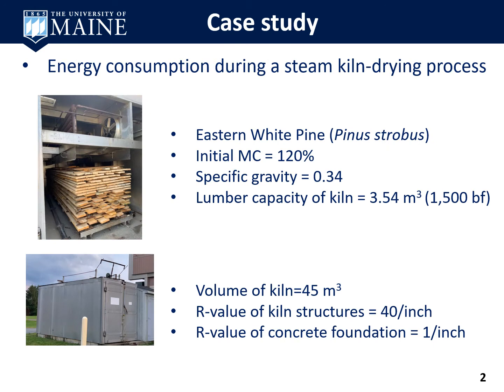Conventional wood drying process, also known as heat and vent drying, is regarded as an energy-intensive process. We did a case study to analyze how much thermal energy is used to heat the cold fresh air brought in the kiln. The wood species was eastern white pine with an initial moisture content of 120% and a specific gravity of 0.34. 1,500 board feet of lumber was loaded into a small steam kiln.